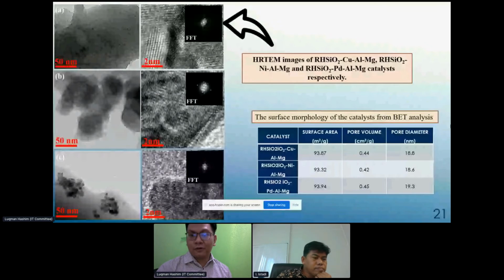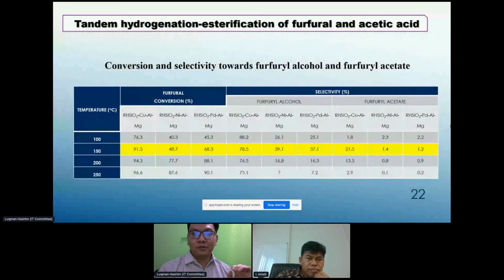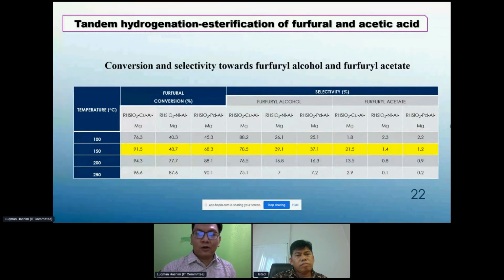The BET also provides similar observations to us, that surface area, pore volume, and pore diameter are very similar in terms of the values from one catalyst to another, for there to be any significant difference to be made. So now let's jump to the actual conversion and selectivity data. Let me just draw you to the yellow bar there. Okay, mainly as you can see, for actual conversion to furfuryl alcohol and furfuryl acetate, it requires a mild temperature. 150 degrees C is actually good for all catalysts.